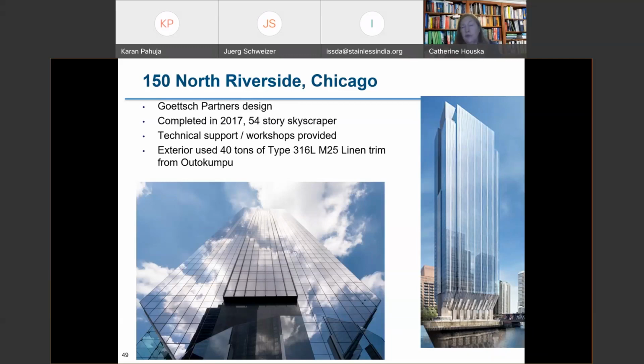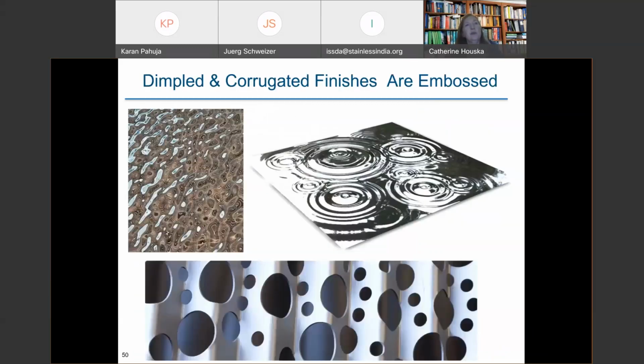So the one finish that has met the requirements of Singapore to date is one that has a very dull substrate with a pattern applied to diffuse the light. In comparison, these are embossed patterns applied to very reflective, bright annealed surfaces on the top, and a duller 2B mill finish on the bottom, which is just to create a sunscreen.